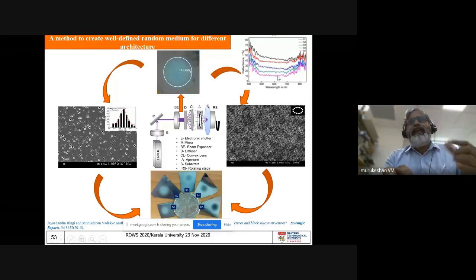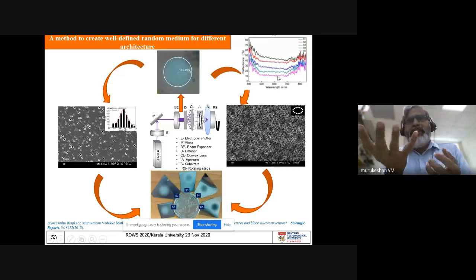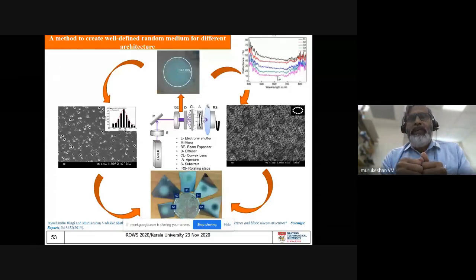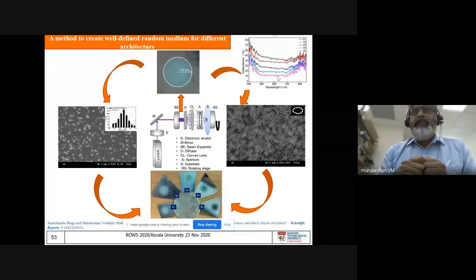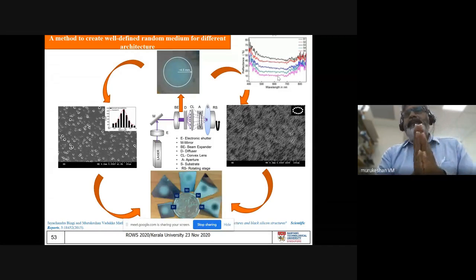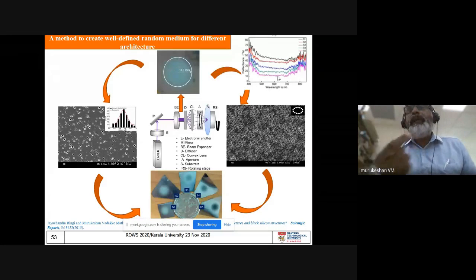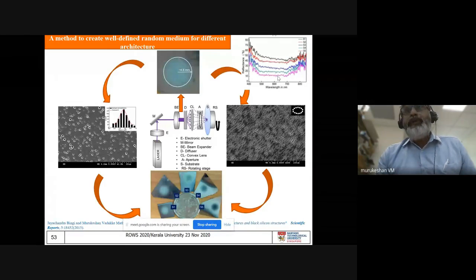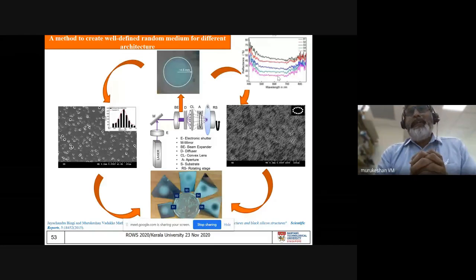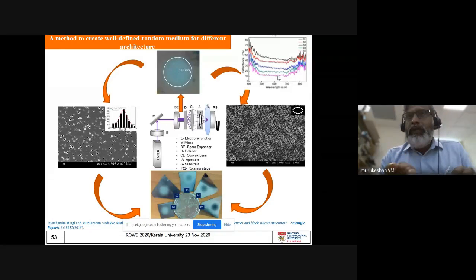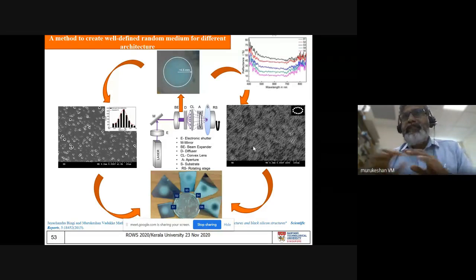What it means is that if you have such a surface, it is going to absorb a large amount of light when it falls on top of the surface. So immediately this was tried with a modular unit of solar cell, and we found that the absorption has been enhanced by a large amount, and that is what we have done. We have also varied this pattern, and we made very black silicon as well. Very bright silicon, mimicking some of the things that you can see in nature.